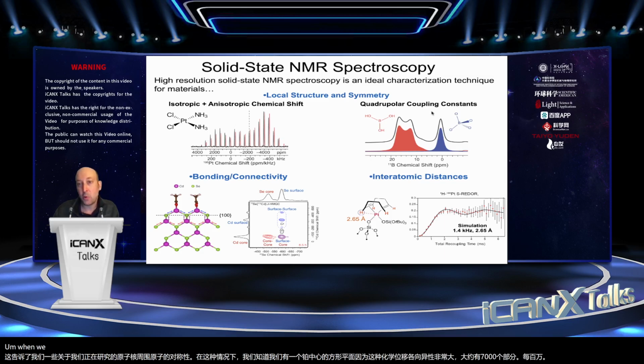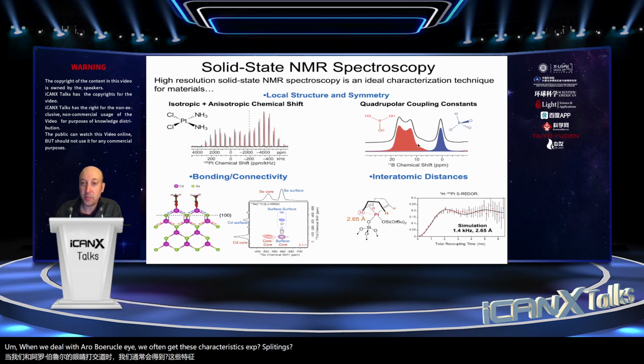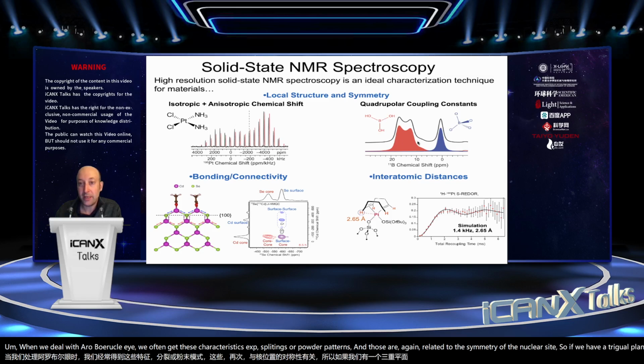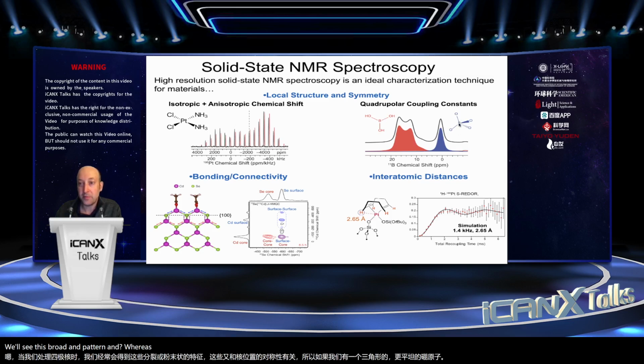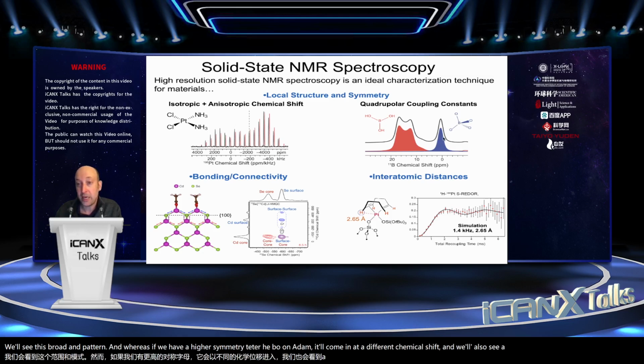When we deal with quadrupolar nuclei, we often get these characteristic splittings or powder patterns, and those are again related to the symmetry at the nuclear site. So if we have a trigonal planar boron atom, we'll see this broadened pattern, whereas if we have a higher symmetry tetrahedral boron atom, it'll come in at a different chemical shift, and we'll also see a narrower pattern.